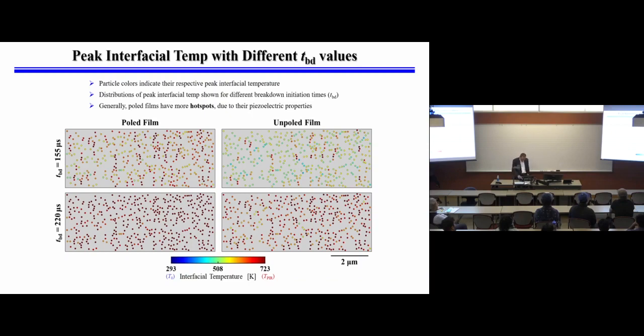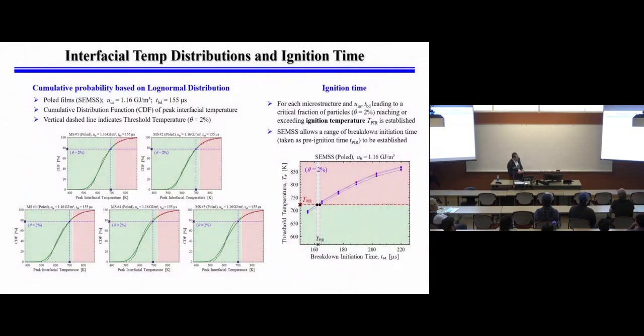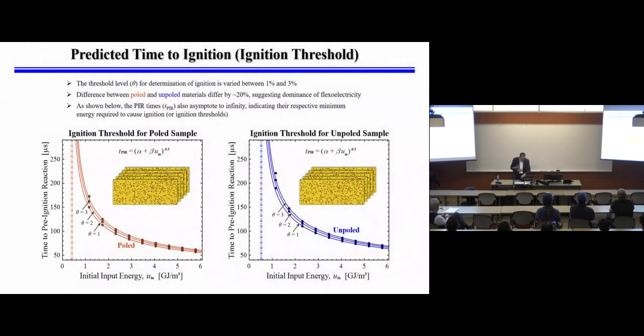We do all that, and then we say how much of the particles or the microstructure is hot enough, has been heated enough to reach chemical reaction. And then we can calculate that threshold. How much time do we need to apply mechanical loading? And we can calculate that. And then for multiple different samples, we can calculate the statistical difference as well. And I would just say that for different levels of required heating, of course the predicted ignition curve, heating curve is a little bit different.